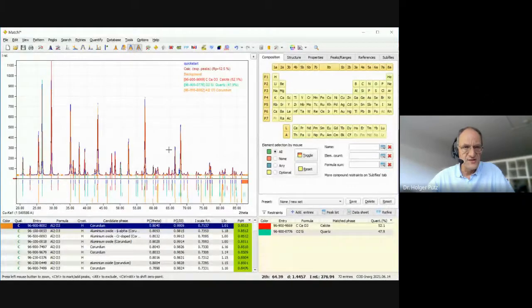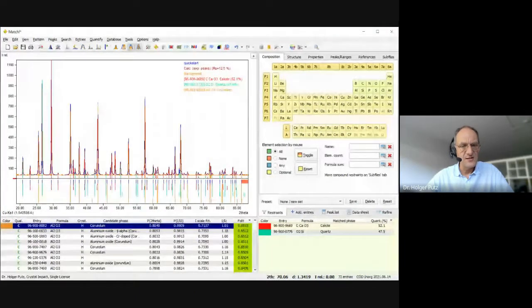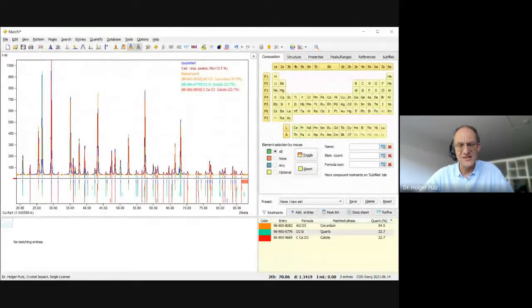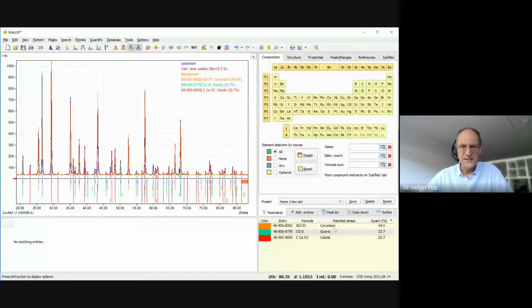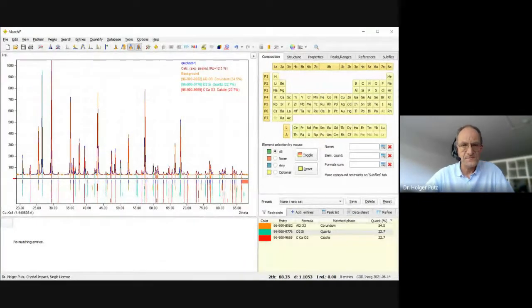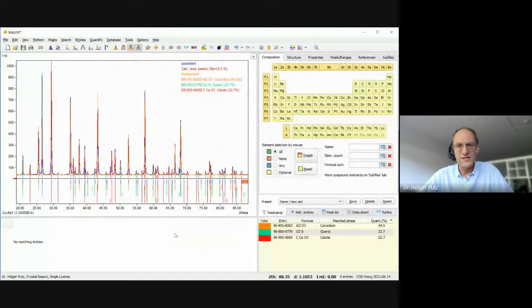Again, the agreement to the experimental pattern is really good, so I would also like to select this as matching. This time I will just press the space bar, which is the third option for how you can select a phase as matching. And now we have three phases here in the match list on the lower right-hand side. And as you can see on the left-hand side, there are no more matching entries, as all the remaining reference database entries have such low figure of merit values that they are no longer interesting here. Okay, that's what the qualitative analysis is about.